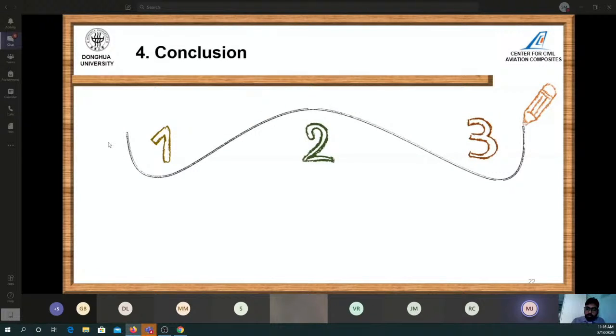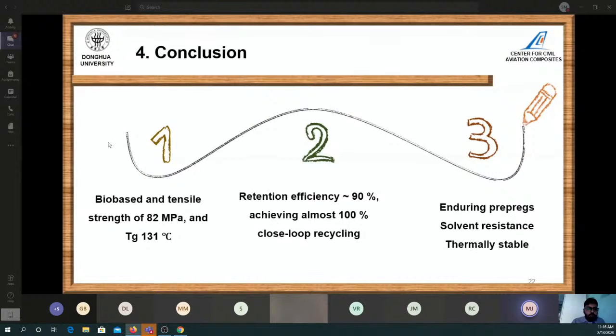Yeah. So these are the conclusions: the bio-based resin's tensile strength was as high as 82 megapascal, and the glass transition temperature was 131 degrees centigrade, with a retention efficiency of 90%, achieving almost 100% closed loop recycling. The additional benefit was that it is thermally stable and solvent resistant, with enduring prepregs.